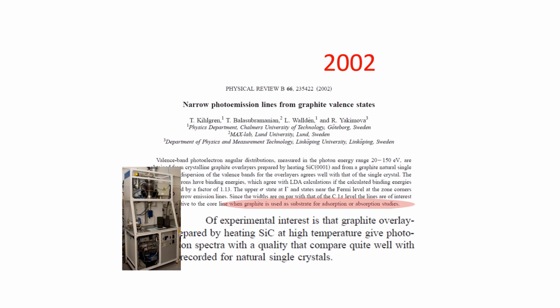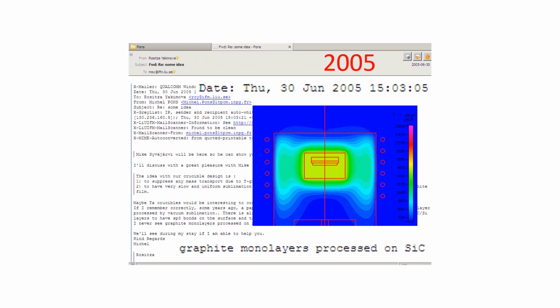So we started 20 years ago for the thin graphitic layers, and then there was collaboration with Chalmers, and they showed that it was very nice quality of the graphite. So almost like the quality of the natural graphite, which you can find in a mine somewhere. And we were curious, so we made these graphitic layers thinner. And then in 2005, we had one layer of carbon on the silicon carbide. So then we were in the graphene avenue. We did not realize what it was useful for, but it was interesting from the growth point of view.